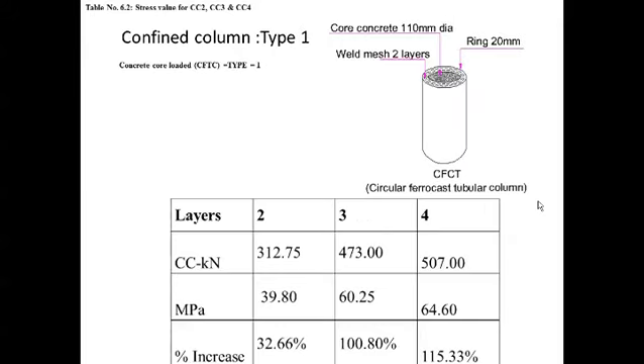When circular confinement was done for plain concrete, this is type 1. In different cases we got strength enhancement with 2 layers, 3 layers and 4 layers of reinforcement used as confinement. The compressive stress we got was almost 40 MPa, with 3 layers 60 MPa, and with 4 layers almost 64 MPa.